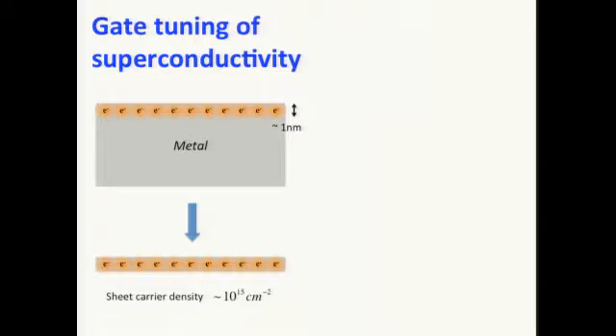But if you actually make the material thinner, even thinner than the Thomas Fermi screening length, now it gives rise to a sheet carrier density of 10 to the 15 per centimeter square using an ionic liquid gate, which is pretty much like a battery in your cell phone, right?